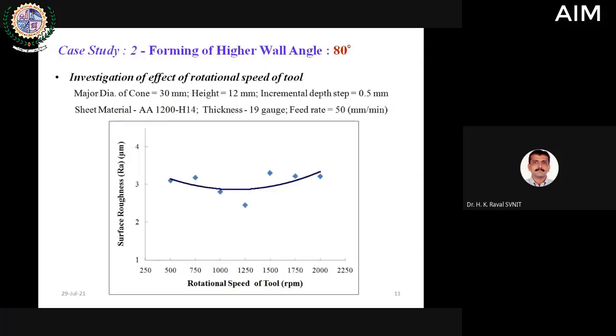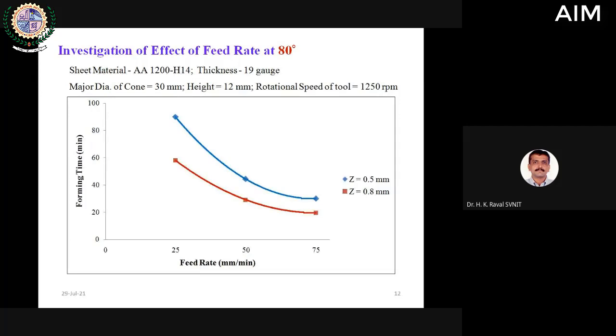Then we even tried changing the feed as well as the incremental depth. We tried different incremental depths of 0.3, 0.5, 0.8. But here I have summarized only two different incremental depths, 0.5 and 0.8. And it is observed that the forming time is always minimum where the incremental depth is more. This is the graph for forming time, not for surface finish. And the forming time is further governed by the feed rate. The higher the feed rate, the lesser the forming time.